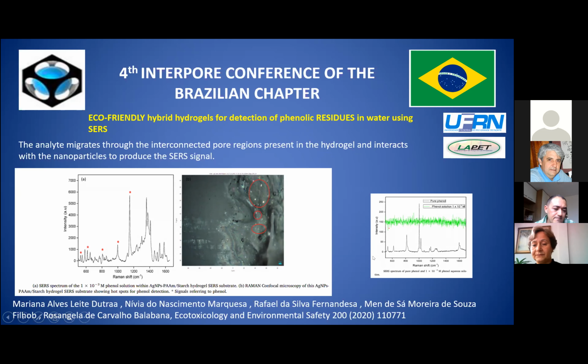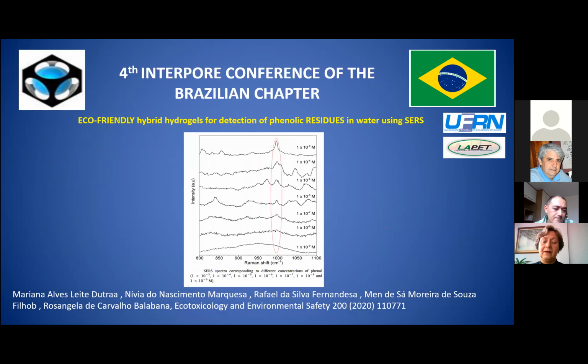In the graph, we can see that in the case of pure phenol, we have a very good Raman spectrum, with a high intensity of the peaks. However, when we decrease the concentration of phenol in aqueous medium, the signals disappear. And using this device, it was possible to detect phenol in very low concentrations, such as 10^-7 molar concentration.